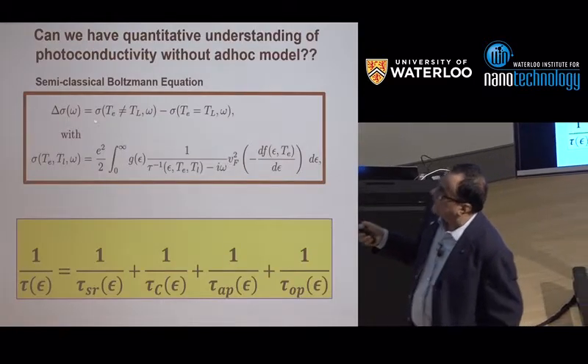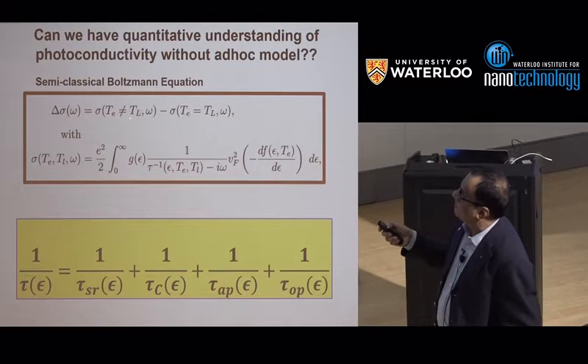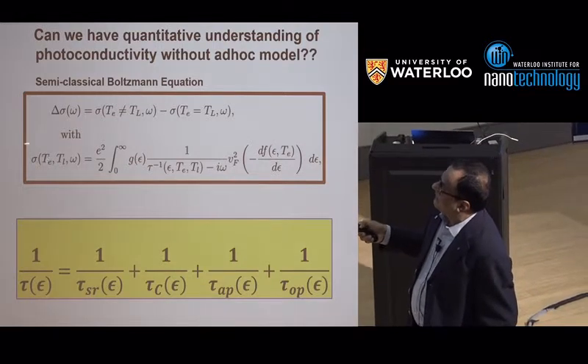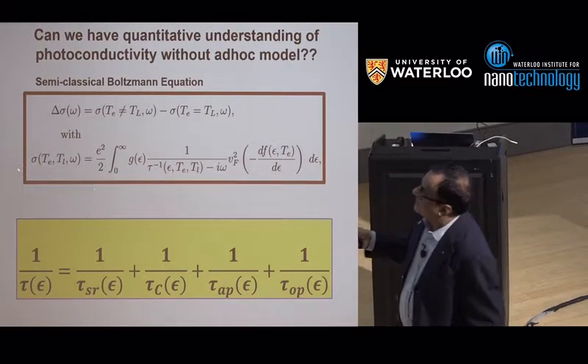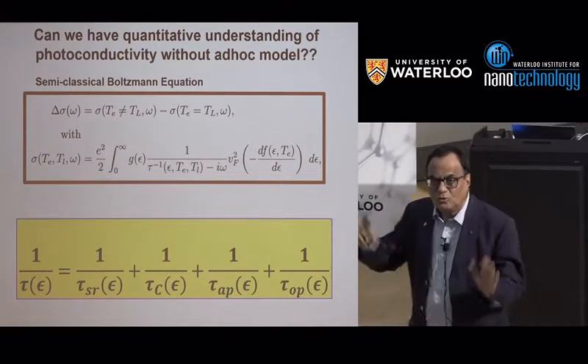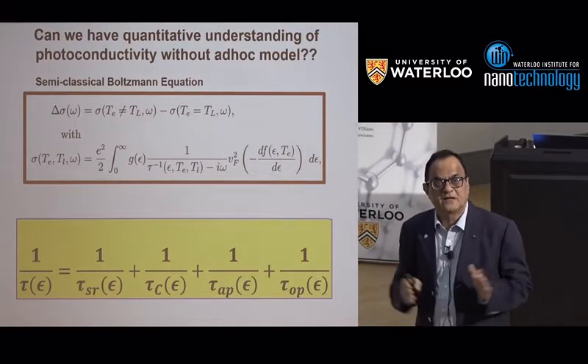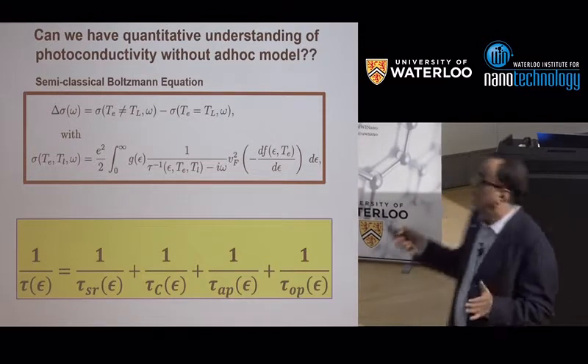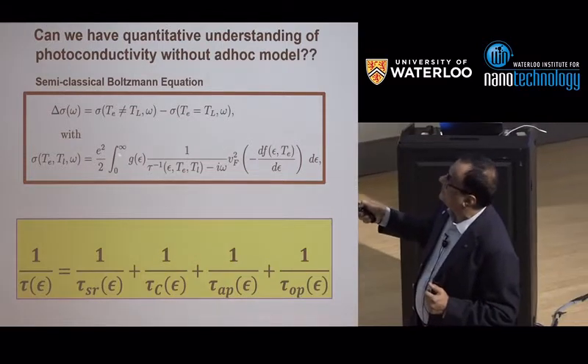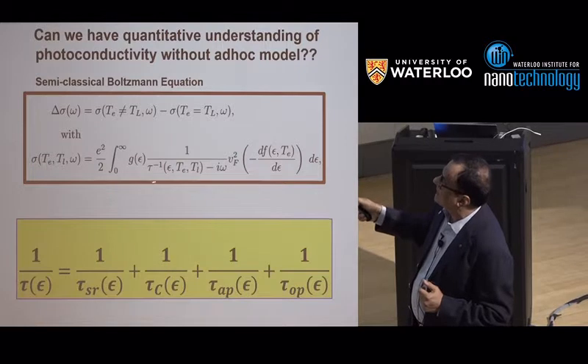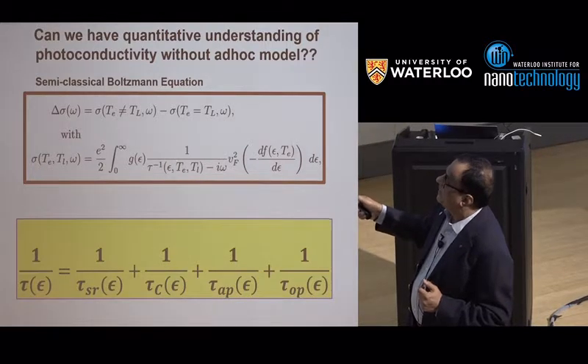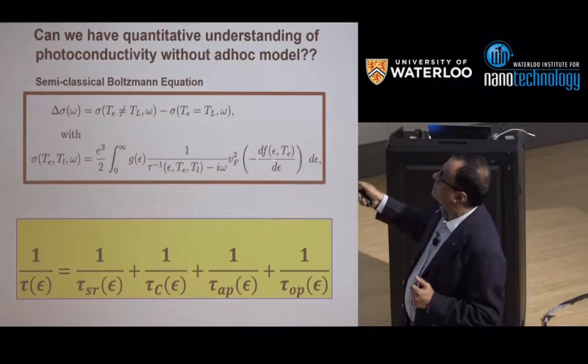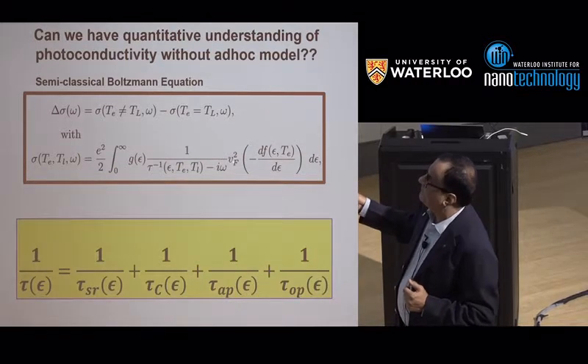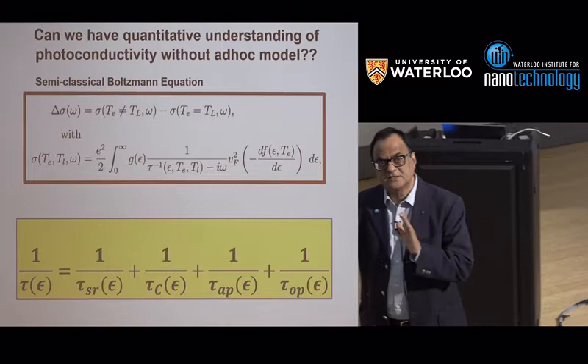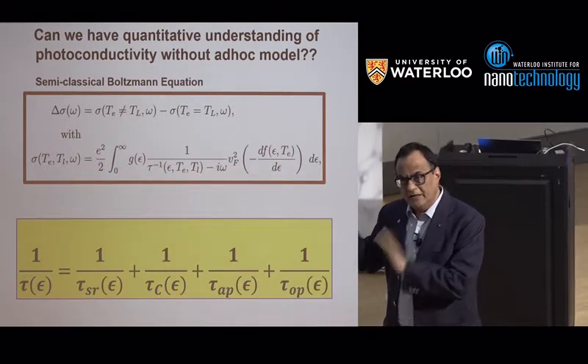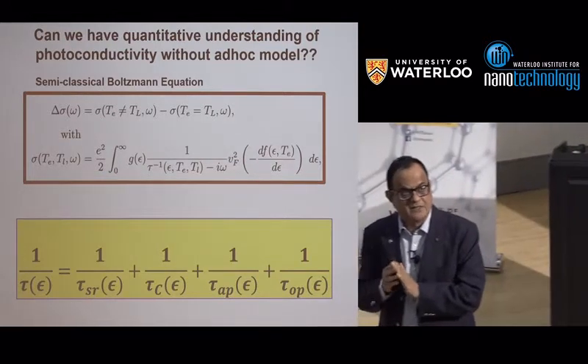So I hope you don't get pushed or repelled by an after-lunch talk with equations. The conductivity is very well known in textbooks. It's a Boltzmann transport equation. You have the density of states of the material, you have the momentum relaxation time, which depends on energy, electron temperature and lattice temperature, you have the derivative of the Fermi function and Fermi velocity. Everything is well, if you can put these numbers, can you really do it?